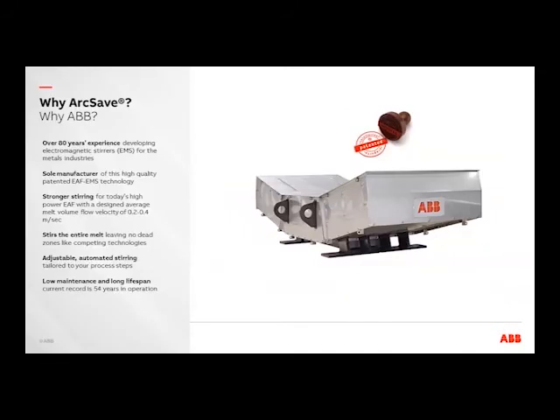So why are we choosing the ArcSave? ABB Metallurgy has a long experience of developing electromagnetic stirrers for different applications. It could be for the slab caster, for billets and blooms, and for the aluminium furnace. We are the sole manufacturer of this technology. We are also creating a much stronger and controlled stirring profile, with a design average melt volume flow velocity of around 0.2 to 0.4 meters per second. We are stirring the entire melt, leaving no dead zones like competing technologies, for example gas stirring, which has a much more localized stirring pattern.